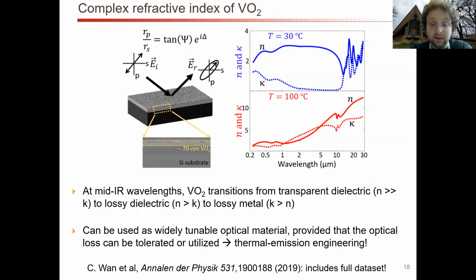And so we in our group at UW-Madison and with many, many collaborators have been exploring the use of various materials which are very, very temperature tunable. Their optical properties depend very strongly on temperature. One such material that's quite well known at this point in the community is vanadium dioxide. Vanadium dioxide, or VO2, has been studied since something like 1960, in part because it has a very complex and very fascinating insulator-to-metal transition. So essentially, if you heat it up past about 70 degrees Celsius, it goes from an insulating semiconducting state to a metallic state. The electrical properties change dramatically, the resistivity drops by something like 4 orders of magnitude, and the optical properties change a lot as well, especially in the infrared, because the Drude contribution is a dominant contribution to the optical properties of the material.